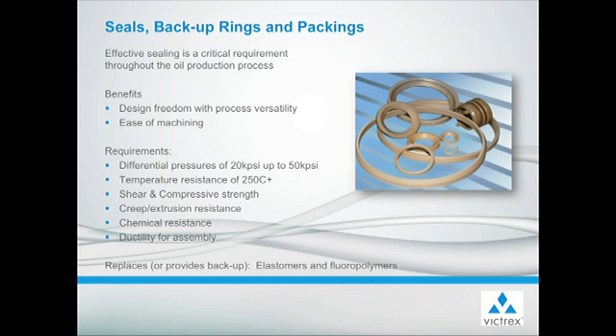Some of the key engineering requirements for these seals are differential pressure resistance from 20 to 50,000 psi, temperature resistance to 250 C and greater, high shear and compressive strength, creep and extrusion resistance, excellent chemical resistance, and ductility for assembly. And these are typically replacing or backing up and reinforcing elastomers and fluoropolymers.